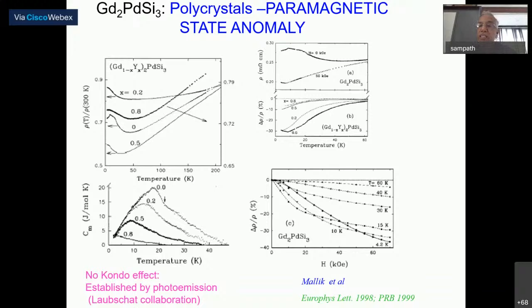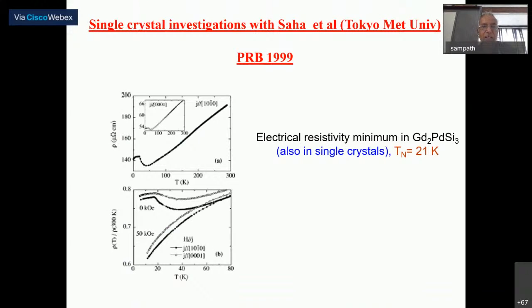Importantly, it is not due to just lattice disorder, because I will show you, we have studied many materials, and this comes only before the onset of magnetic order. It is magnetism related. I will produce more proof on that. Anyway, since the referees raised doubt on the sample, we also measured on a single crystal, and you could see the minimum persists even in the single crystal before the magnetic ordering. Similar magnetoresistance here. So this clearly suggests the data is quite genuine. We published in 1999 in Physical Review B on that.